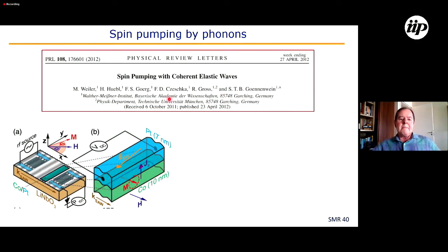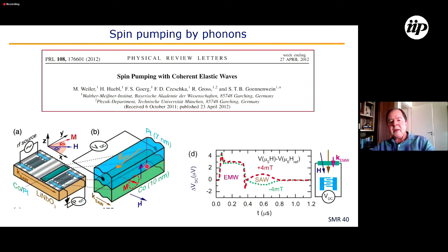Now, in 2012, this gentleman made spin pumping with elastic waves, phonons. The experiment consists of using elastic transducers. The transducer converts an electric signal into phonons in a piezoelectric material, and the phonons propagate in the cobalt, which is a ferromagnetic material that has a platinum cover on top, and they measure a pulse corresponding to the pulse of the phonon. If they reverse the magnetic field, the polarity of the pulse reverses. So this voltage is due to spin pumping by phonons.